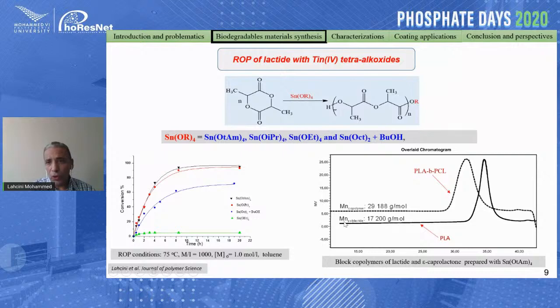We also used it to prepare block polymers, polylactide-block-polycaprolactone. We start the polymerization first with polylactide, and at the end of the conversion we add caprolactone. As you can see, we have two lines. The continuous line is the first polymer, and the discontinuous line is the block polymer. As we have monomodal curves, this indicates that we have polylactide linked to polycaprolactone, so we have a block copolymer.